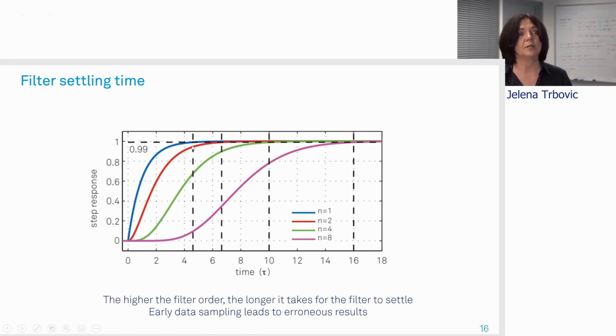We can see here that the first order filter takes about 5 time constants to settle or to reach the full signal amplitude. And if we have an especially noisy system, we are basically forced to increase the number of filters in the demodulation chain, and we might end up having to wait about 10 time constants before the filter settles.